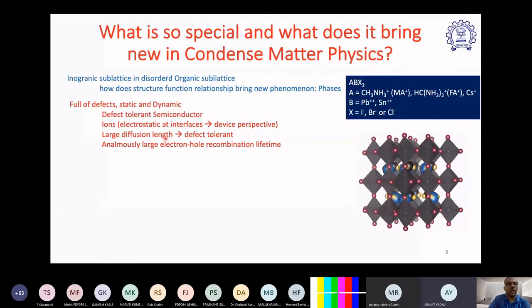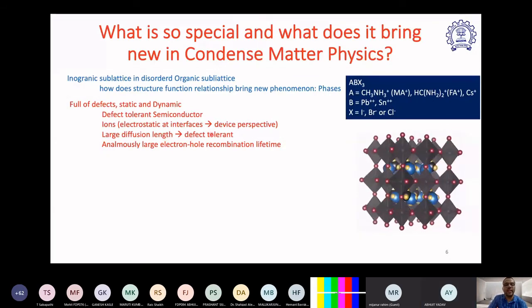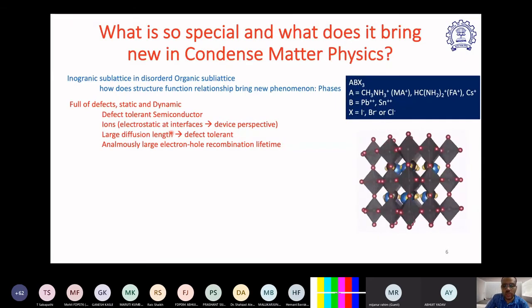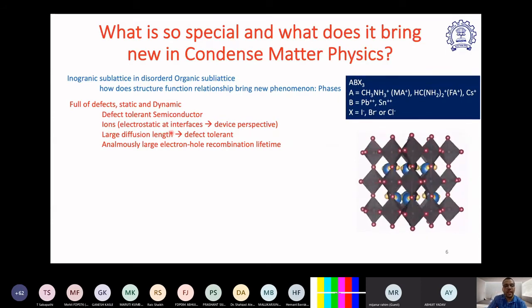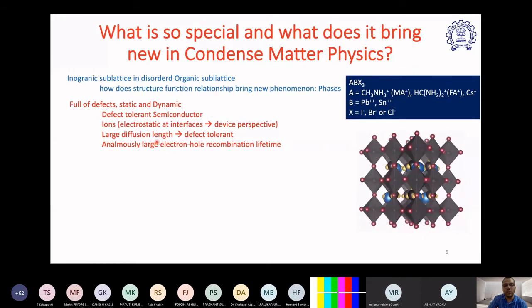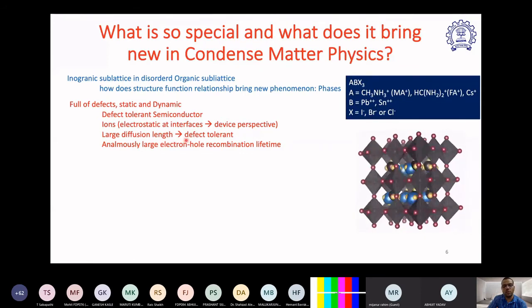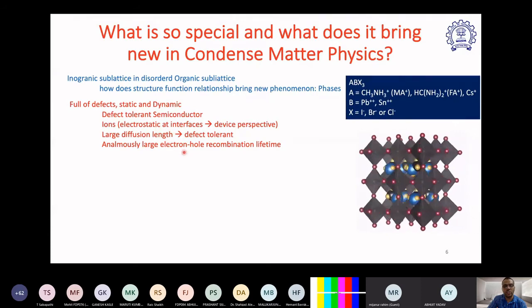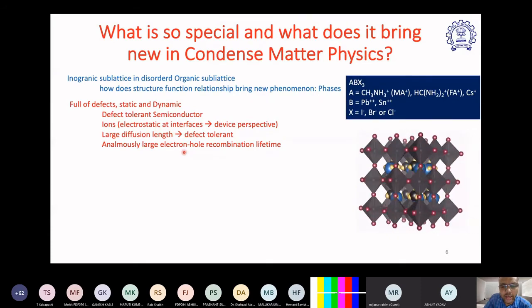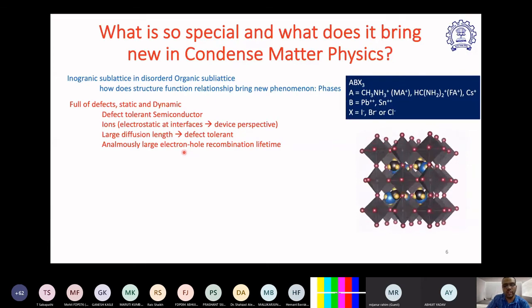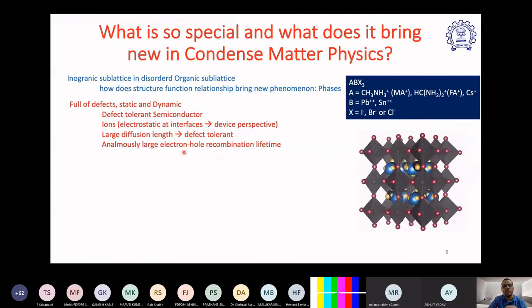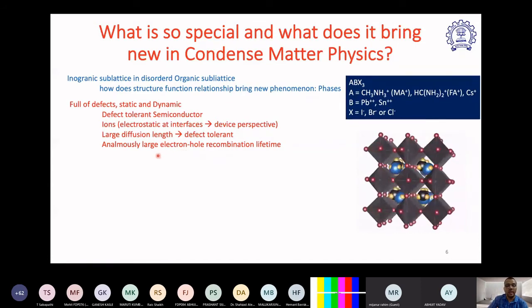And at the same time, as I was telling, the lattice ions are sitting there, which should create a problem for charge transport, but somehow we don't see those kinds of problems. I will tell why that happens. There is a very good, large diffusion length, and that is expected because we already said these are defect tolerant semiconductors. Charge transport is somehow maintained because if defects are there, they are being healed by molecules which are freely available to heal those defects.